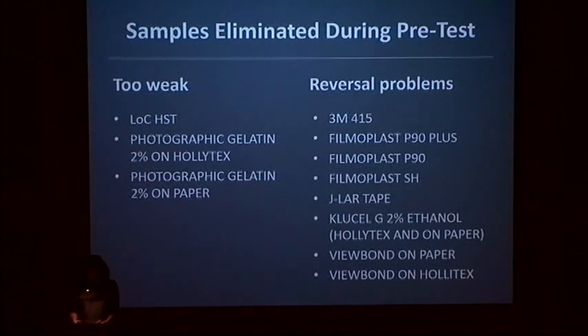Adhesives that did not make this cut are listed here on your left. These are the ones that didn't pass the shear test. On your right, you have the results for the removability test. So 14 of the original 50 combinations of adhesives and carriers failed in the pretest. It's about 28% of the total 50.